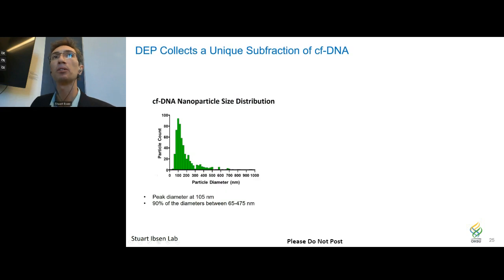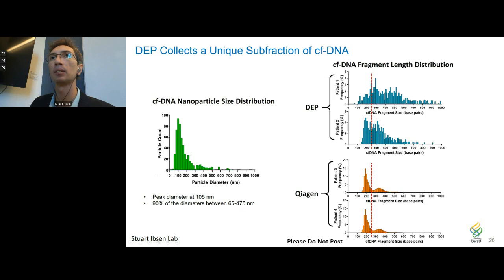So of particular interest are the cfDNA nanoparticles. We were able to look at the size distribution of these DNA nanoparticles and found that they have a peak diameter around 105 nanometers. So right in the area that we would expect based on how particles are being collected. But what was really surprising to us was the distribution of the fragment lengths. So it turns out that the dielectrophoresis, the nanoparticles being collected on these chips, is enriching for a different or a special subset of overall circulating cfDNA.